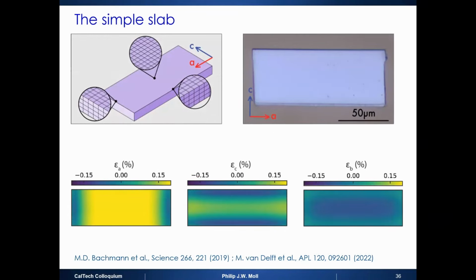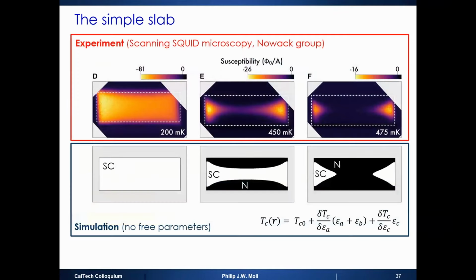Surprisingly rich physics you get from the most boring device, which is a simple slab. This slab is a micron thick, cerium iridium indium 5. Really key is that one direction is the C direction and one direction is the A direction. Everybody looks at the tetragonal system, everybody looks in the AB plane. But now this is an AC plane of this intermetallic. Imagine you pull on it in all directions. In its center, it will be non-distorted, distorted in both ways the same, but as you go further to the edges, for example here, it will be more pulled in this direction, whereas on the other edge, it will be more pulled in the other direction. Now one makes TC go up, the other one makes TC go down.